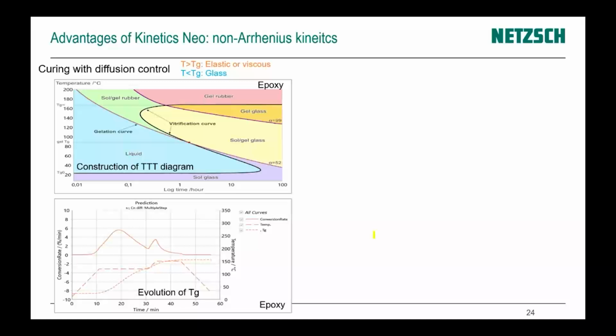Also, Kinetics Neo can work with non-Arrhenius kinetics. For example, Time-Temp Construction can calculate or construct a simulation for a time temperature transformation diagram. And here we have the gelation line, vitrification line, and we can see where the material is liquid, where it is elastic, where it is sol-gel, where it is rubber or maybe glass, and so on.